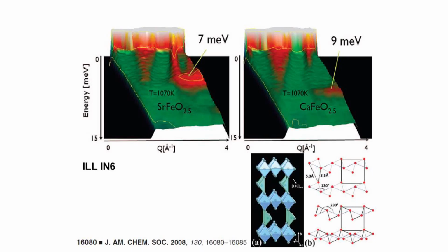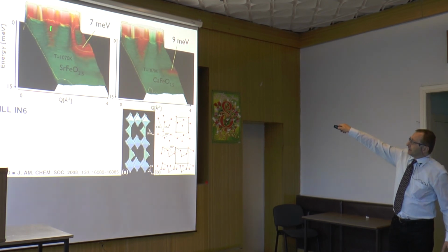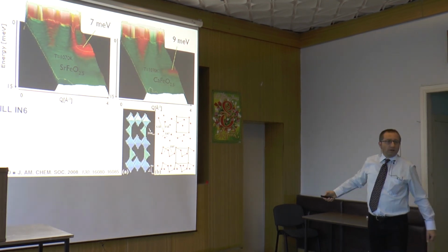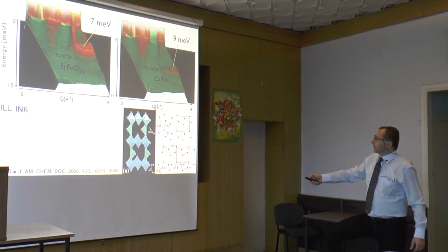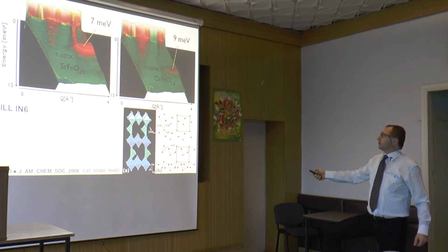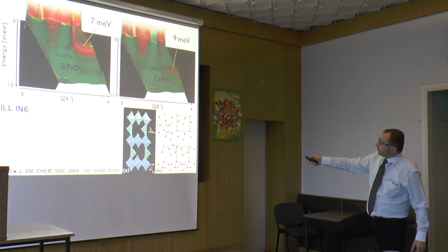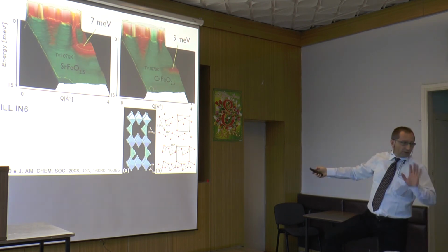Also, if we look at the quasi-elastic scattering, this is the Bragg peaks. This is the inelastic scattering, and this region is the so-called quasi-elastic scattering. Here you see the phonons in the momentum versus energy plot. And in the system which is conducting, you see the phonons that link the system to the elastic peaks, while in the non-conducting system, this mode is isolated.